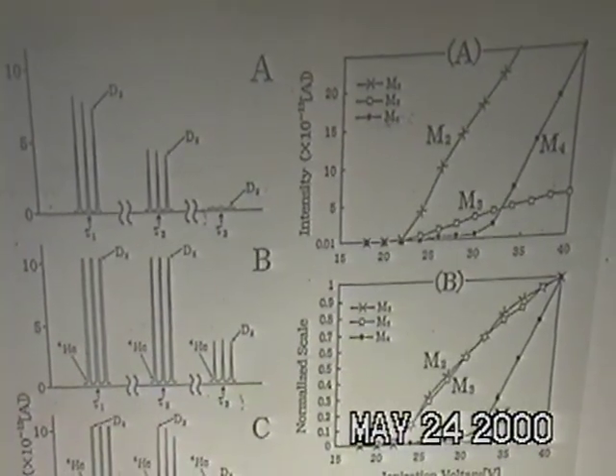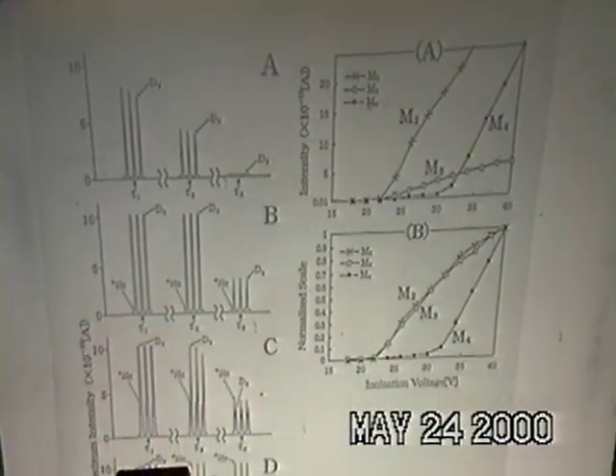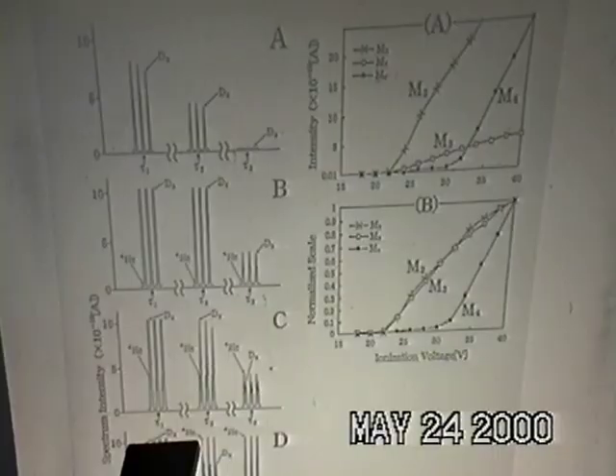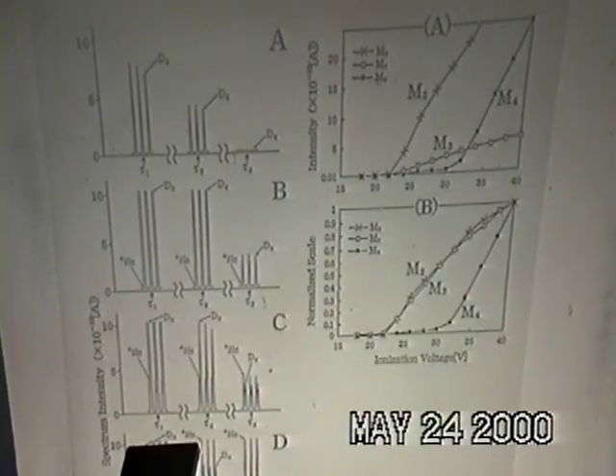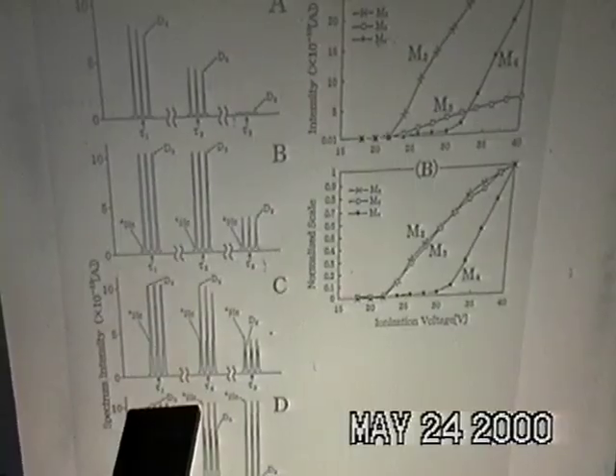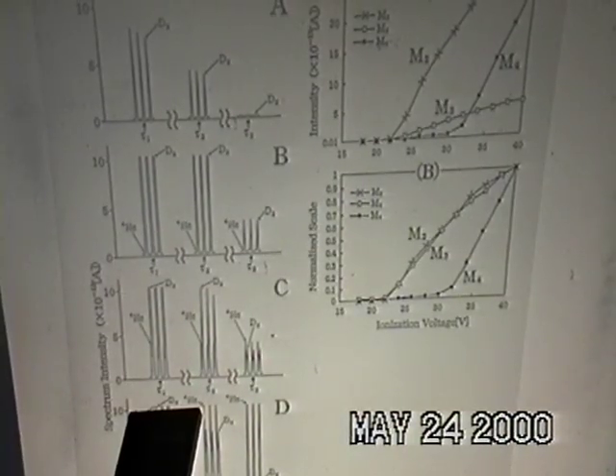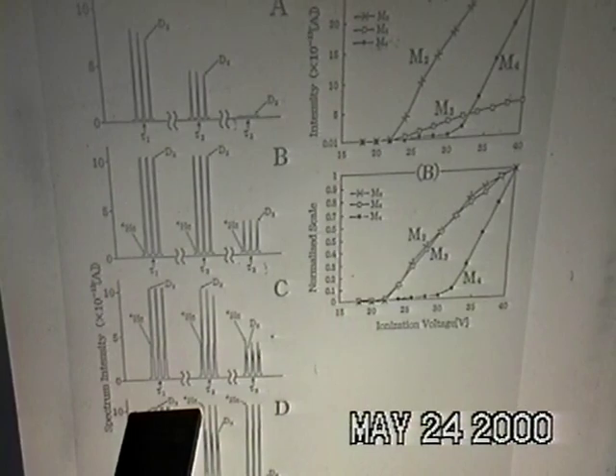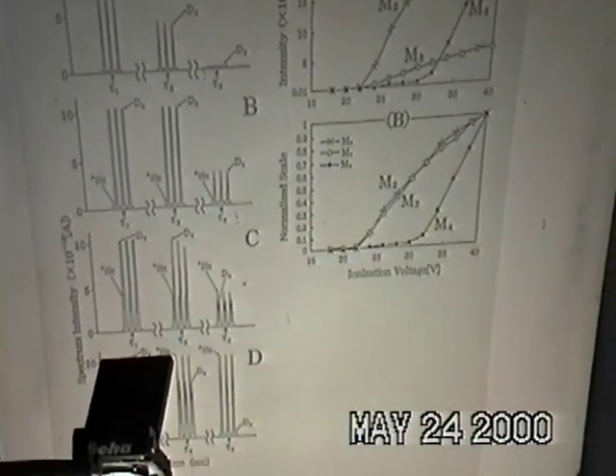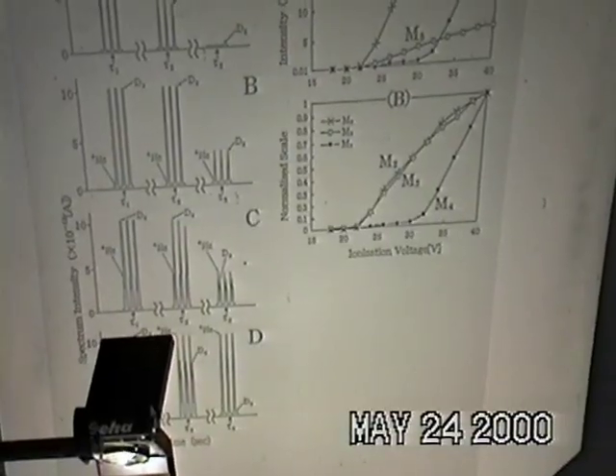Left side diagram shows a couple of spectra of mass 4 with D2 and M4 obtained by our developed closed QMS with A-type piercing system. When the DS cathode was set up inside the tank with very high vacuum, the gases inside the DS cathode ought to leak into the tank through the cathode wall. This situation is the first stage before piercing and plays a greatly important role in this experiment.